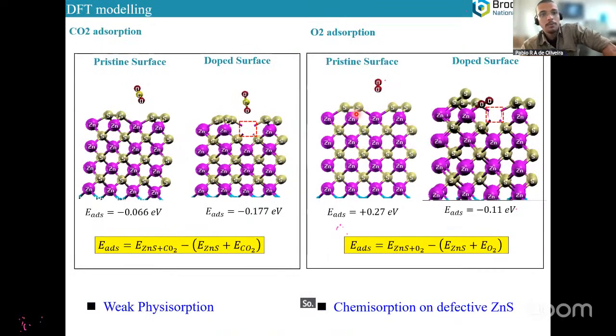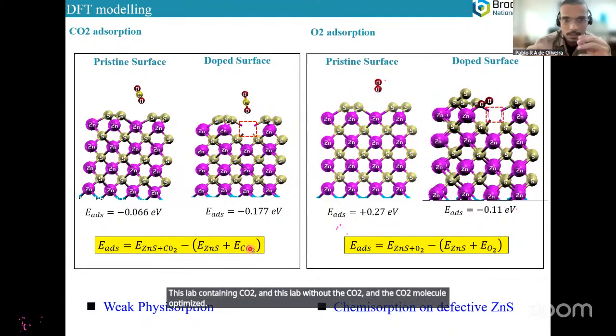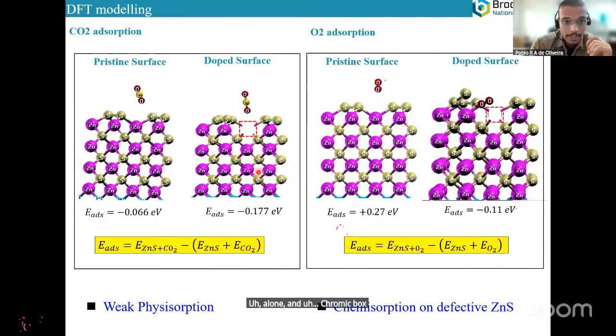So now we try to figure out these findings from a DFT perspective. For this, we compute the adsorption energy as shown here. Basically, you have this slab containing CO2 and this slab without the CO2, and the CO2 molecule optimized alone in a cubic box. And if you look at the adsorption energy, we can see that indeed, when you have zinc defects, marked in this dashed rectangle, they display a lower adsorption energy. So probably the defective ZnS surface is responsible for interacting with the CO2 molecule.